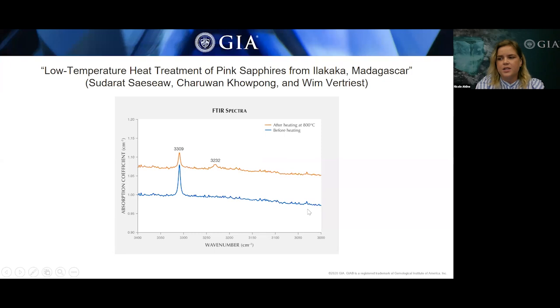And then as it was heated, a 3309 series developed, which is that 3309 peak with a 3232 and/or a 3185 peak. Now in this study, all the samples showed a decrease in their 3309 peak after being heated, and 9 of the 11 developed a 3232 peak, with no 3185 peak being observed.